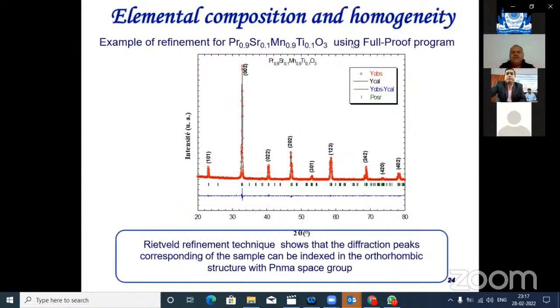Let's move on to some research. Here is an example of a refinement of this kind of sample using the program for X-ray diffraction. The Rietveld refinement technique shows that the diffraction peaks corresponding to the sample can all be indexed in the orthorhombic structure, and no impurity was observed in this sample.